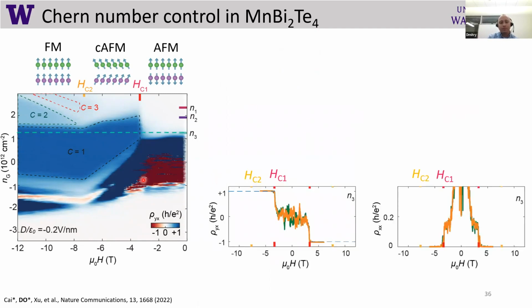So for that purpose, we can make line cuts. In the first line cut, when we cut at a fixed carrier density as a function of magnetic field, we can see this immediate quantization. And I just want to pay your attention to the fact that this is canted antiferromagnetic Chern insulator. So it's a little bit different, or actually a lot different from, for example, traditional MTIs, where your ferromagnetism is always out of plane. In this case, in canted antiferromagnetic state, we have small out of plane moment, but we also have in plane antiferromagnetism, which is pretty interesting.